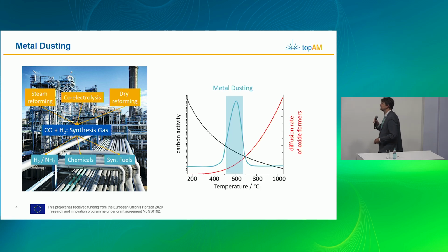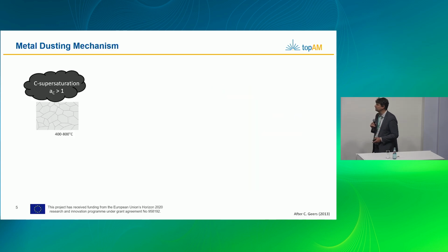Now, the problem with this gas is that it causes a severe kind of corrosion at around 600 to 650 C that eats up the plants pretty fast. Interestingly, above that temperature, the scales, for example alumina or chromia, that form protective scales on the metals grow faster, and the carbon activity also goes down. Below that, under 400, the kinetics are too slow. So it's really these medium temperatures that are the most severe.